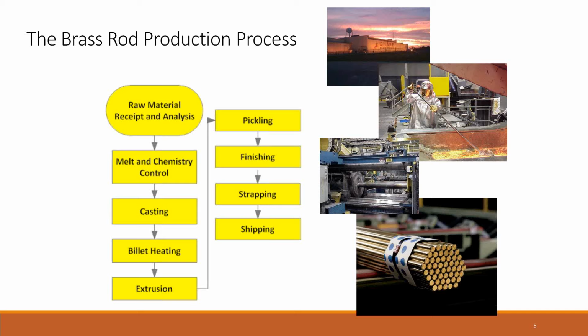Castings are either direct chill continuous cast, or they might be horizontally continuous cast, and you're making a large diameter billet that's going to get cut and then heated up to make it soft and malleable. And on average, for most of the alloys we're talking about, it's about 1350 Fahrenheit that you have to heat that material to, so that you can get a broad range of sizes extruded out of your extrusion press in preparation for the cold drawing operation.